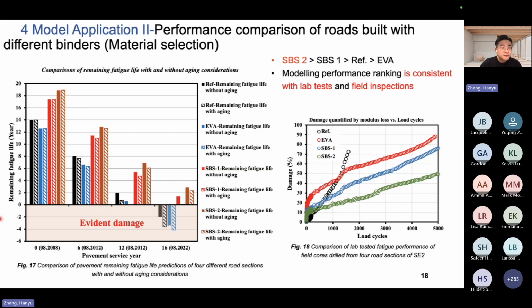In this slide, the left figure shows the comparison of the pavement remaining fatigue life predictions of the 4 trial sections with and without aging considerations. And the right figure is a comparison of the laboratory tested fatigue performance of the field cores. What we see here is that the modeling performance ranking is consistent with the laboratory test results as well as our field inspections, as shown in the experimental part.